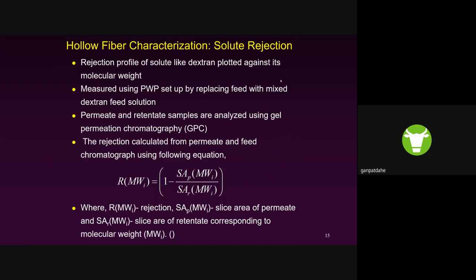So in general, what they do is create a mixture of different polysaccharides, such as dextran, from 5,000 molecular weight all the way to a few 100,000 molecular weight. They pass that mixture through the lumen of the hollow fiber, and they measure the concentration of the dextran in the permeate as well as the retentate side, and based on that, one generates the rejection curve. And this is really important to find the molecular weight cutoff of the membrane.